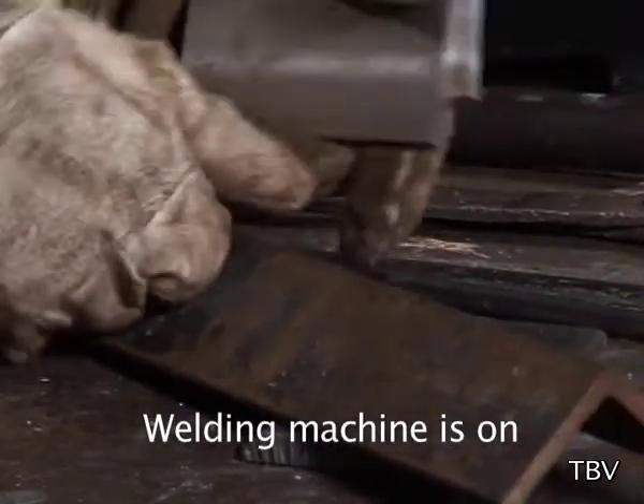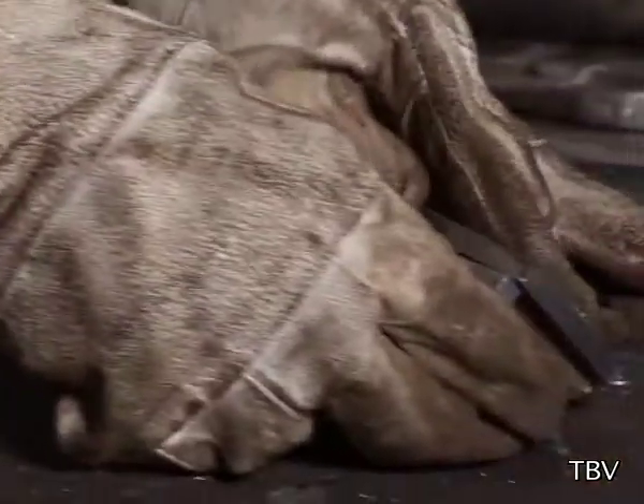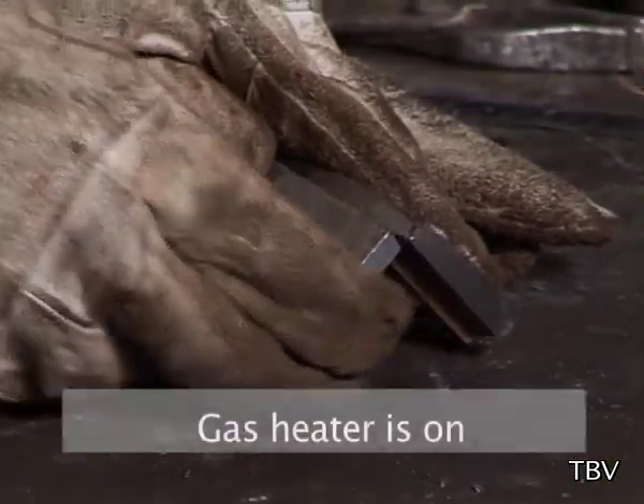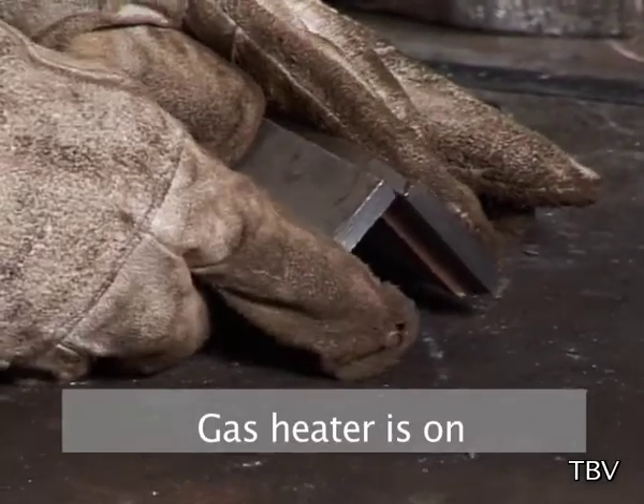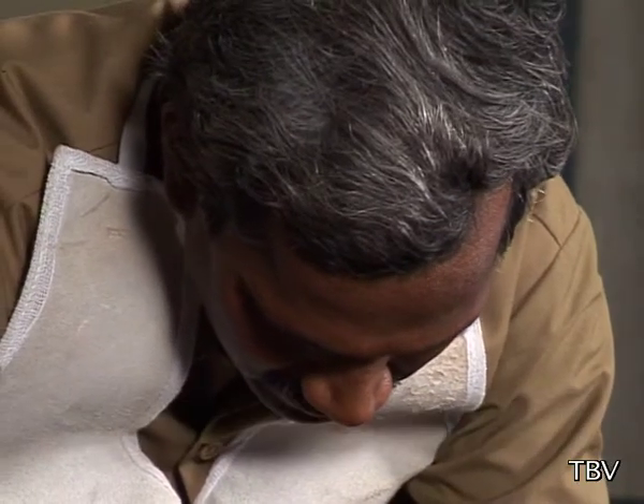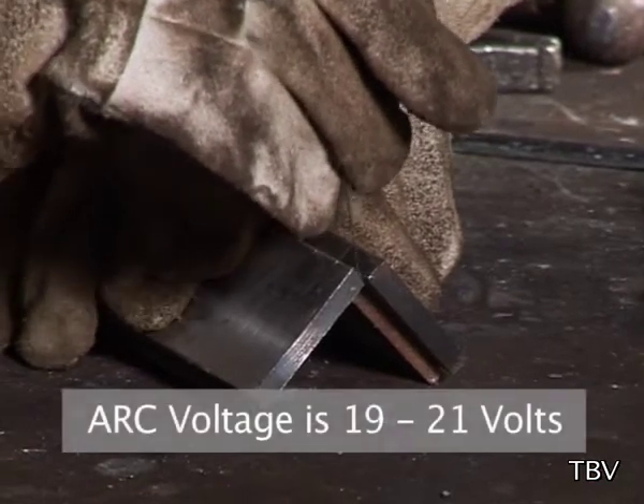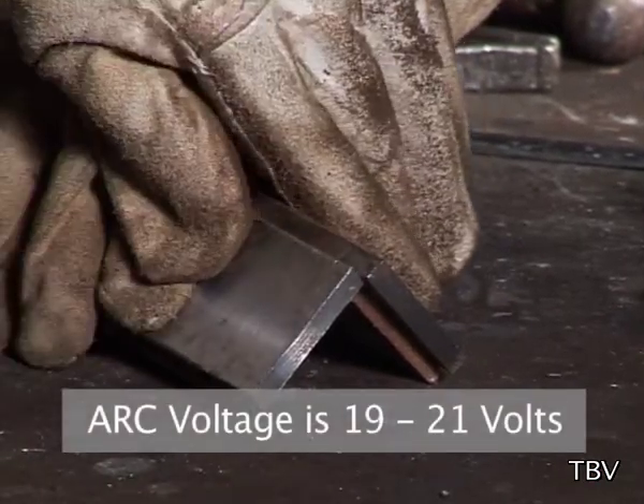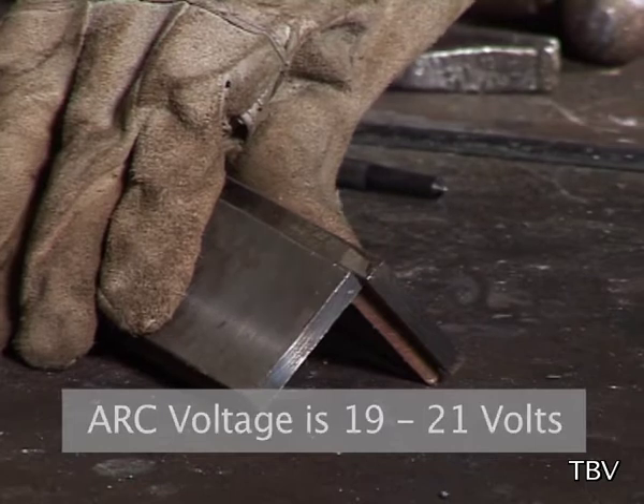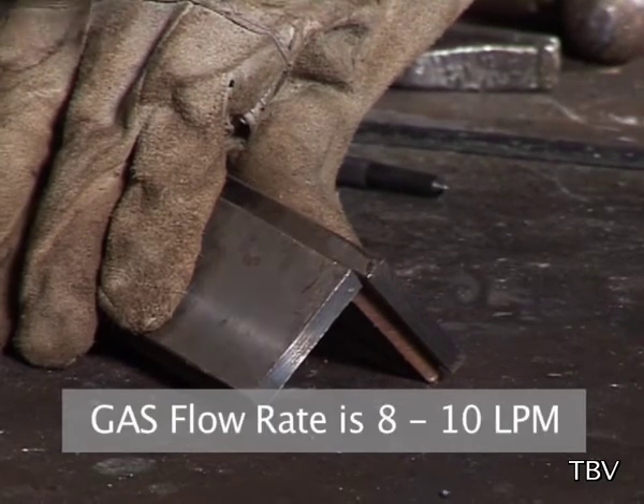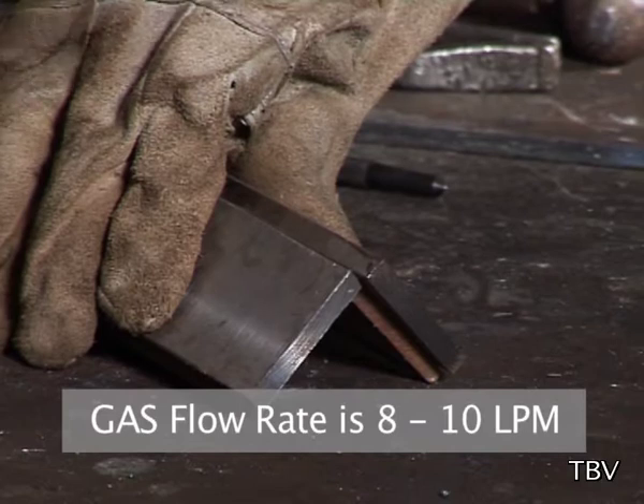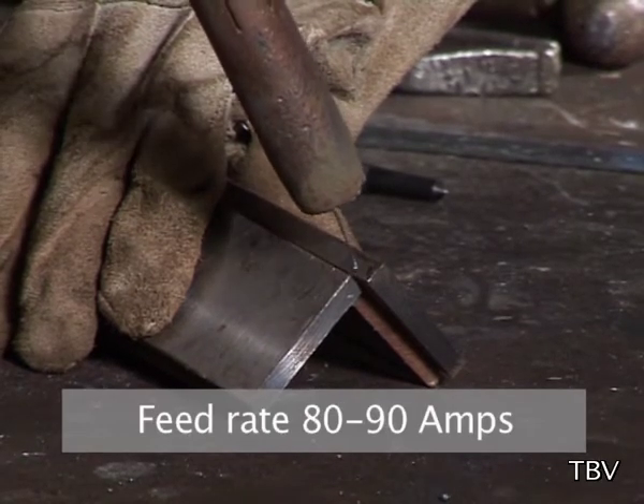Exercise 9. Fillet weld outside corner joint on MS plate of 10 mm in vertical upward position. You have already seen the preparation of the job piece. Let's move on to the exercise straight away. 0.8 mm spool is fixed. Set the arc voltage at 19 to 21 volts as required for dip transfer mode. Set the gas flow rate at 8 to 10 LPM. Set the feed rate.